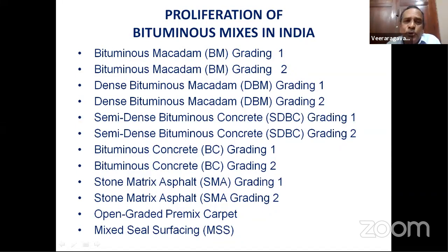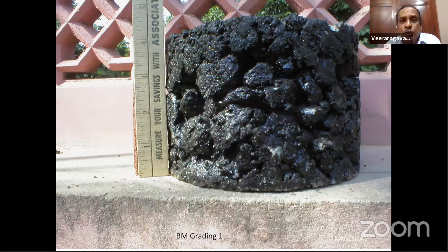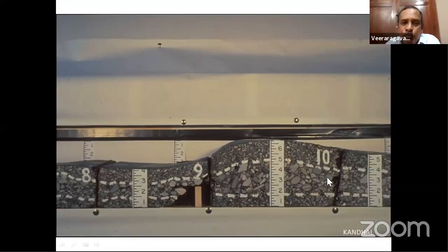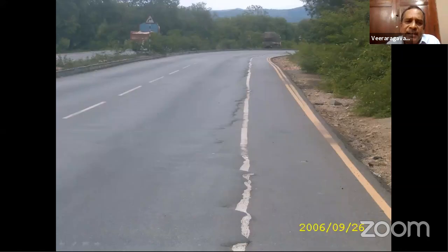But when you try to use BM, we find that there are too many voids. And that's why myself and Professor Kandhal have been advocating. Many other states have banned the use of bituminous macadam. But even in the case of DBM, there are two gradations. Grading one has more voids. Segregation will be an issue. There can even be rutting in the DBM layer alone. So this is again a case of a shear failure on NH7.